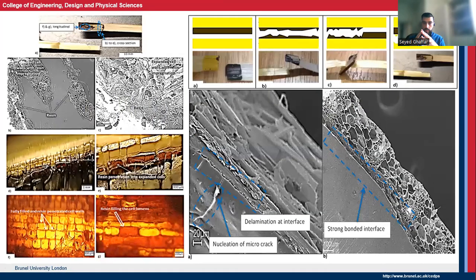So this is the microstructure study of what happens when individual straw internodes are connected to each other and then pulled apart. In the case of untreated straw, we can see that as soon as we have some tension, there is nucleation of microcracks, that is then translated to delamination at the interface and separation and very low strength. Whereas when we have hot water followed by steam pretreatment, we have a very strongly bonded interface.